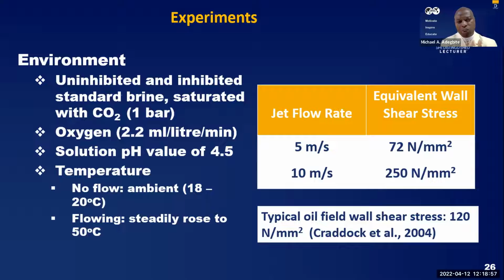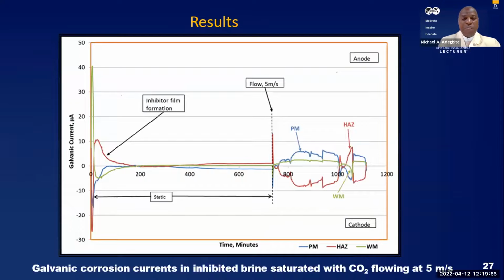So tests conducted in stagnant system, in a flowing system with 5 meters per second, and that 5 meters per second is typical of a wall shear stress of about 72 newtons per meter squared. And at higher flow rate is associated with 250 newtons per meter squared. Whereas the typical oil field condition, we have a wall shear stress of about 120. So this particular method affords us to even go beyond typical flow field situation.